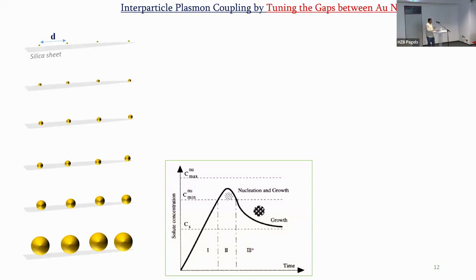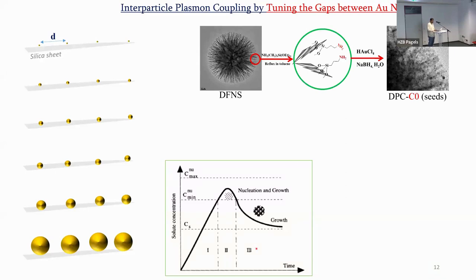And this is possible by tuning the reducing agent, right? If we first use borohydride, which is a strong reducing agent, you reach the nucleation stage, supersaturation, very fast. Afterwards, we change the gold solution to K gold solution, the K salt of HAuCl4, which is much less reactive. And we also change the reducing agent to formaldehyde. So that means now you are not able to achieve supersaturation. You will never achieve nucleation, but you still have the gold atoms, which will go and sit onto the existing gold seed, and that will allow you to grow the gold nanoparticle.